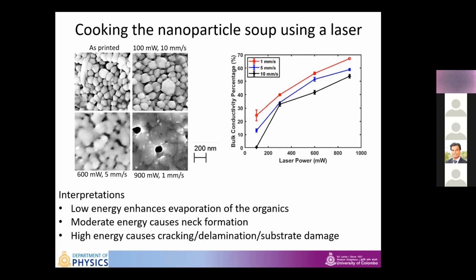At relatively higher energies, for example, the fourth picture, we see further increase in grain growth and neck formation. However, there are some dark spots visible on the trace. Those are possible heat damage to the substrate and also other effects causing delamination of the ink from the paper. The heat damage is not good, delamination is not good. So this is an interplay between two counteracting phenomena, increased necking versus heat damage, that causes the conductivity to saturate at higher energies.